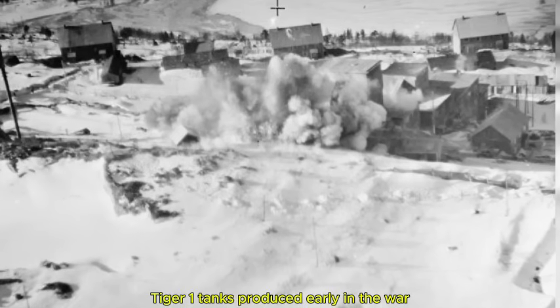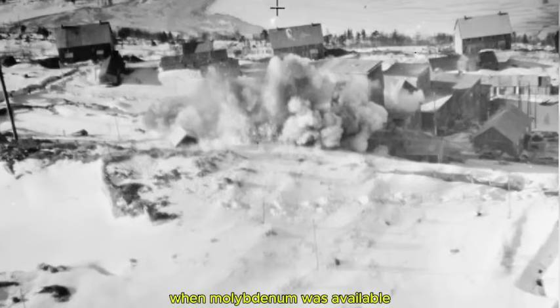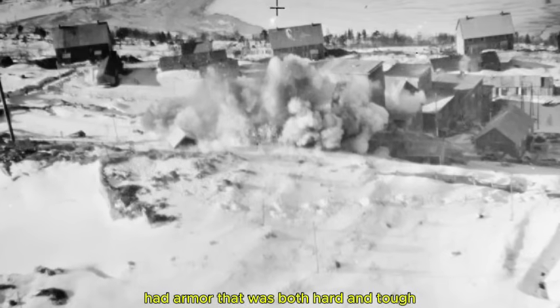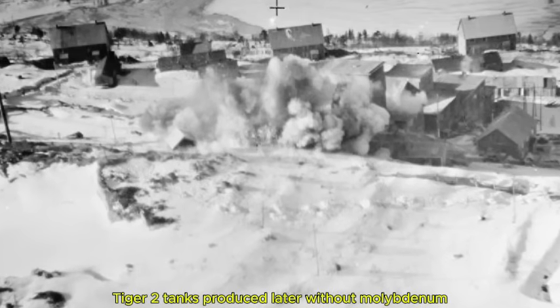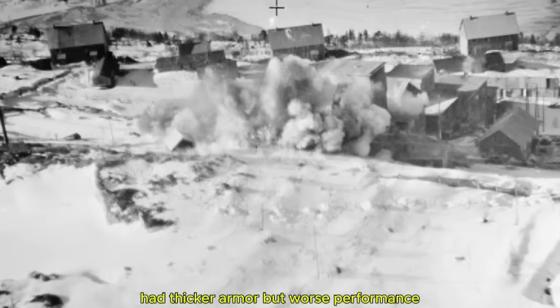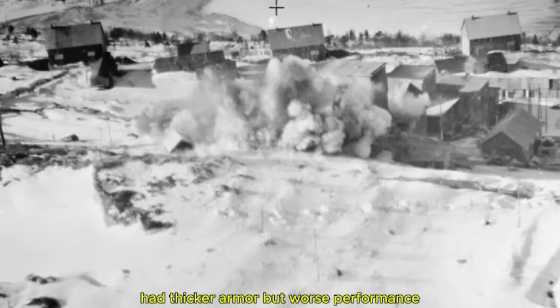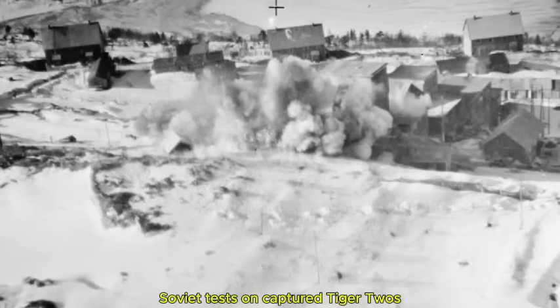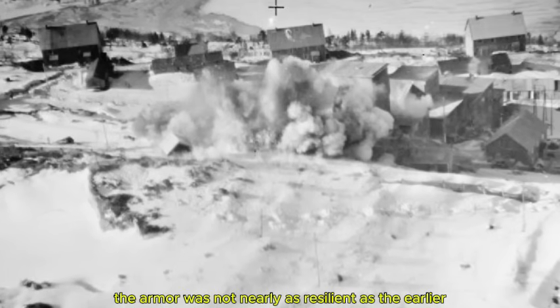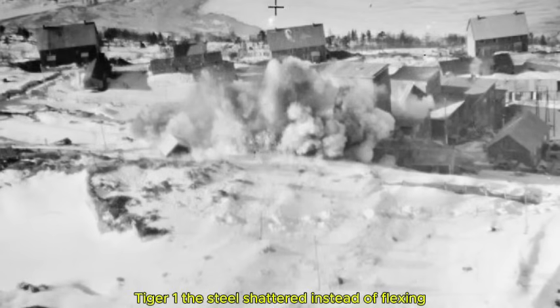Tiger I tanks produced early in the war, when molybdenum was available, had armor that was both hard and tough. Tiger II tanks produced later, without molybdenum, had thicker armor but worse performance. Soviet tests on captured Tiger IIs found that the armor was not nearly as resilient as the earlier Tiger I.